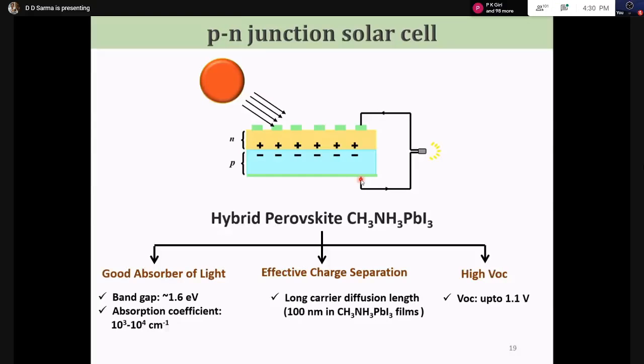And since the solar spectrum is maximum in that range, and from some very detailed balance calculation, it turns out the optimum gap is about 1.4 electron volt. And this particular material has about 1.55 electron volt gap. So it absorbs most of the solar spectrum, and it absorbs with extraordinary efficiency. It has an absorption coefficient which is extremely high. It has a very long carrier diffusion length, hundreds of nanometers. And it has a high open circuit voltage, up to 1.1 volt. So it looks like this material was ideally made by nature to give us high photovoltaic efficiency.